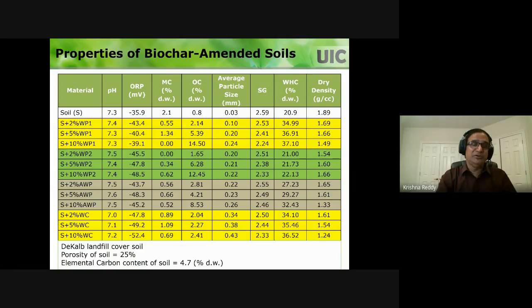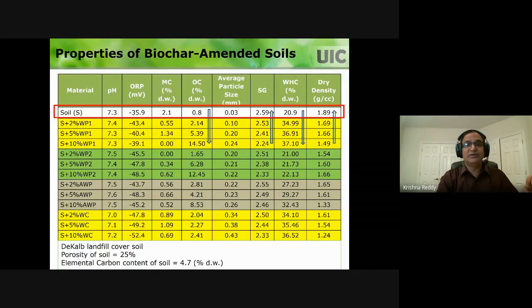A lot of times, you may use this biochar by mixing it with soil in your applications. When you have a soil with certain properties, you add biochar in different amounts, let's say 2%, 5%, 10%. Generally we go maximum up to 20%, and you are going to change the characteristics of the soil. For example, organic content is going to increase. On the other hand, biochar is a lighter material, so your specific gravity is going to decrease. Water holding capacity is going to increase, so dry density is going to decrease.